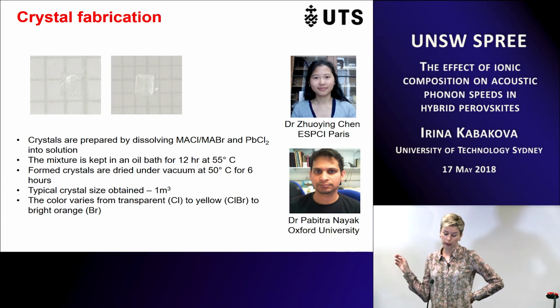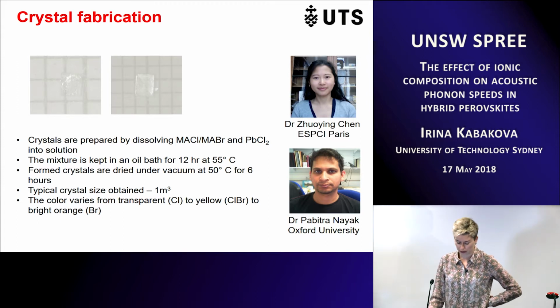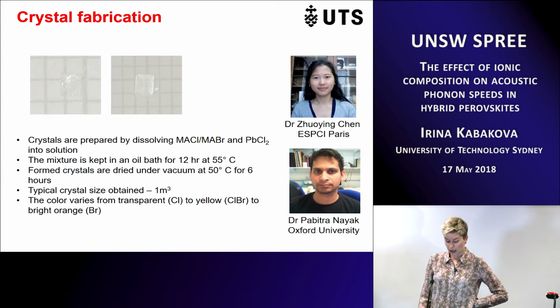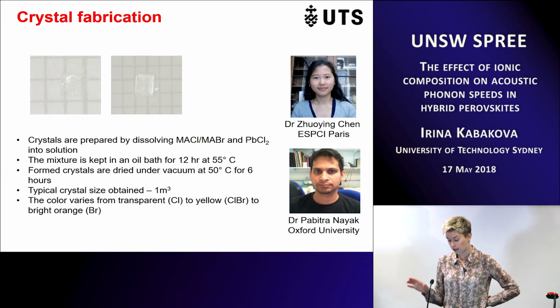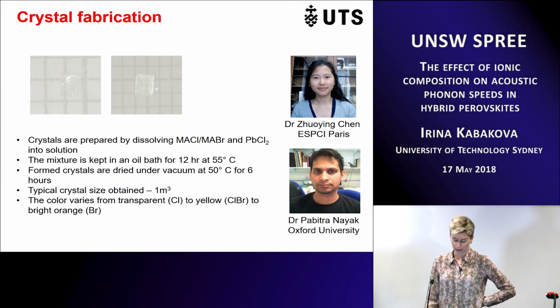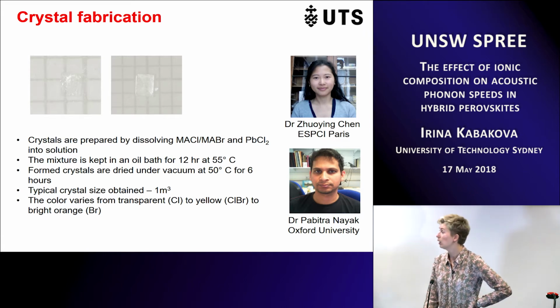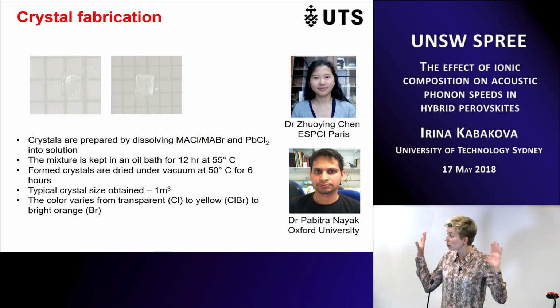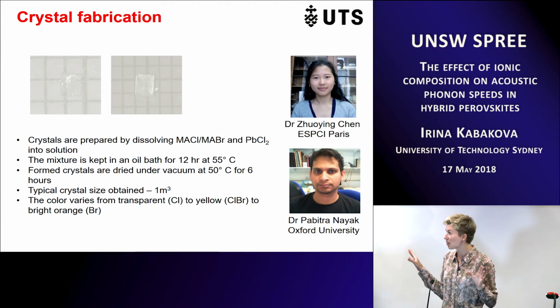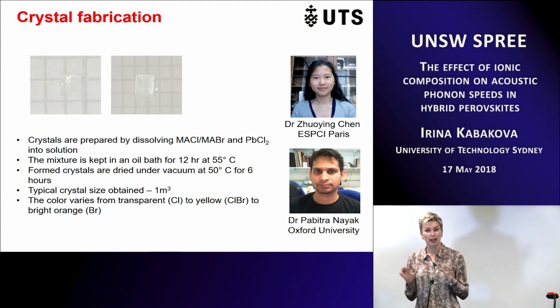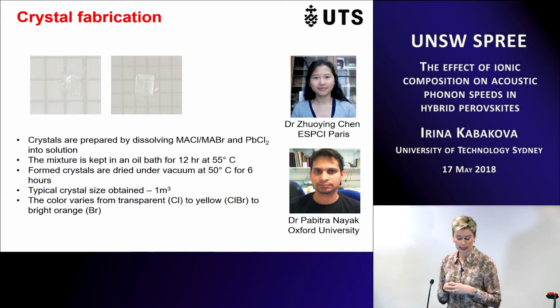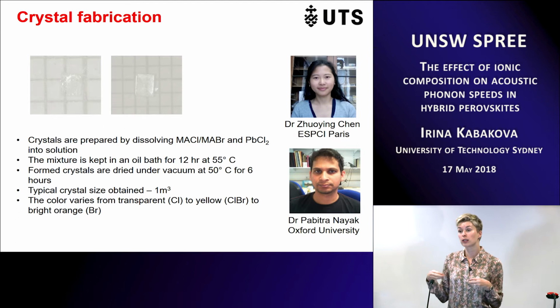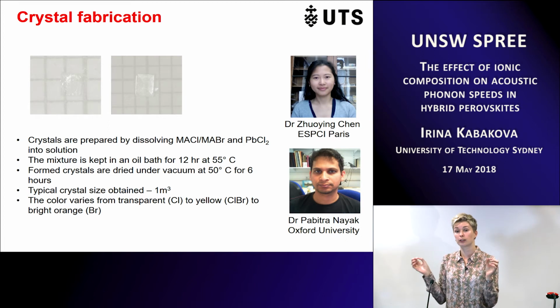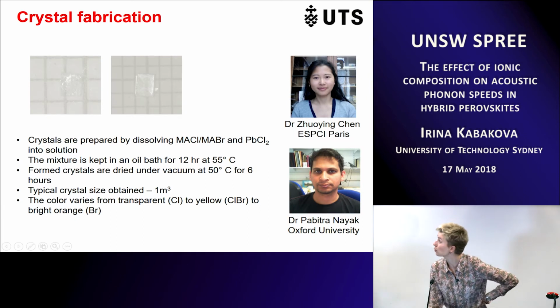The methylammonium perovskite crystals were fabricated in Paris by Zhuoying Chen, and the formamidinium crystals were fabricated in Oxford. Nonetheless, despite the differences in locations, they were made approximately the same way, I mean the fabrication technique. They were prepared out of solutions and then kept at an elevated temperature of 55 degrees Celsius for 12 hours. The crystals formed and then they were dried under vacuum, and we obtained these beautiful crystals.